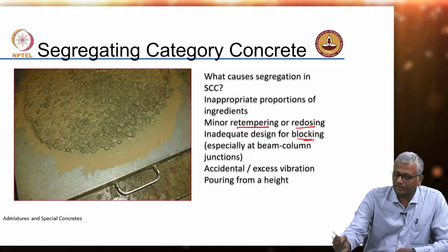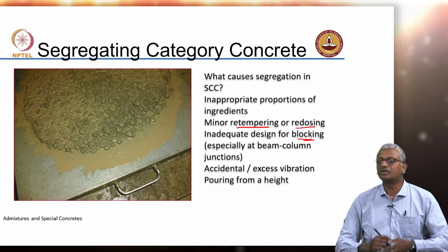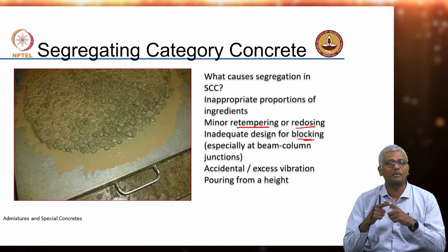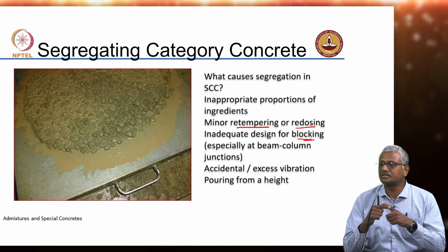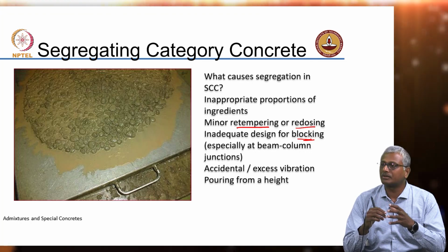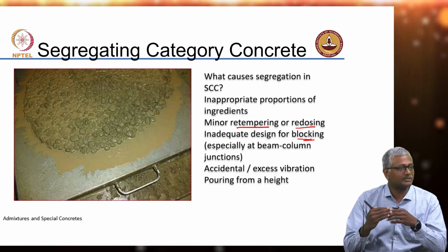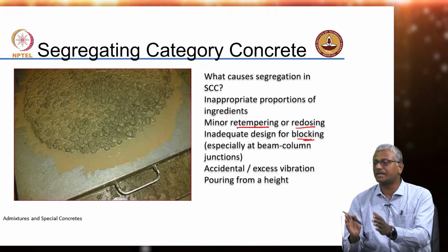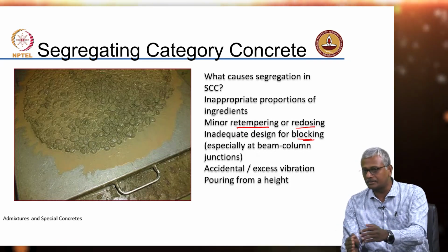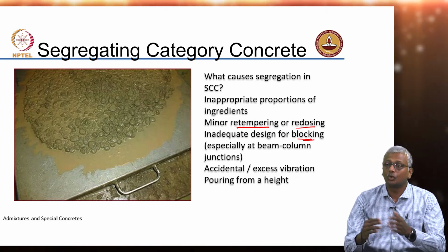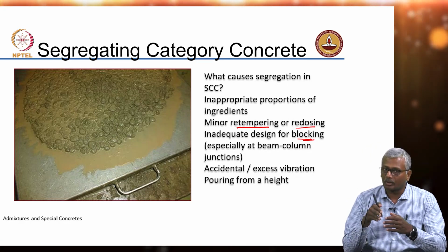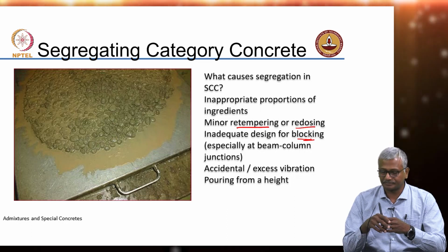Inadequate design for blocking, especially when you have reinforcement congestion and beam column intersections. In those locations, if you are not designing your SCC to actively pass around the reinforcement by adopting suitable test strategies, I'll come back to that later when we describe the test, you can have blocking in those locations.